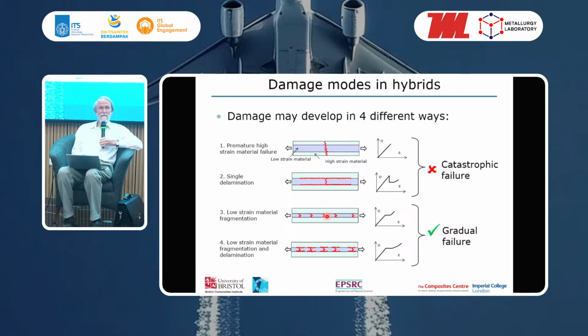However, if you make the carbon thinner as well, then there's not enough energy to propagate that delamination. And so when the carbon breaks, there is not enough energy to propagate the delamination, and so it just breaks at one point, and actually then you can get a break at another point, and you can get this progressive fragmentation. And it can either be like this, where the plies just fragment, or you can get a little bit of delamination locally, but not enough to join up and cause a complete load drop like we get here. And in these cases, with the thin plies and not too much carbon, then we can generate a plateau on the stress-strain curve and get this pseudoductility.